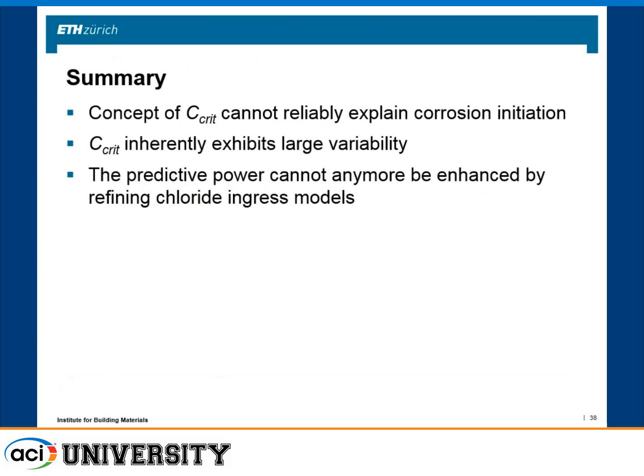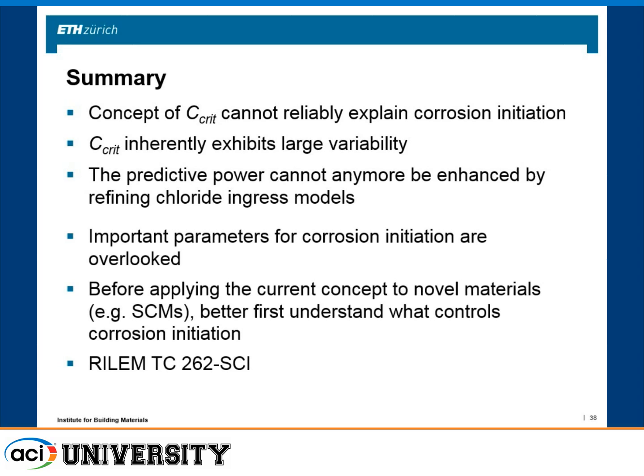To conclude: the concept of the critical chloride content or chloride threshold value cannot reliably explain corrosion initiation, and the predictive power of this concept cannot be enhanced by improving chloride ingress models. Important parameters for corrosion initiation are overlooked in this concept. Before applying the current concept to novel materials, we should first understand what really controls corrosion initiation. A new RILEM Technical Committee established last year deals exactly with the question of how aspects of the steel-concrete interface influence corrosion initiation. Thank you very much.